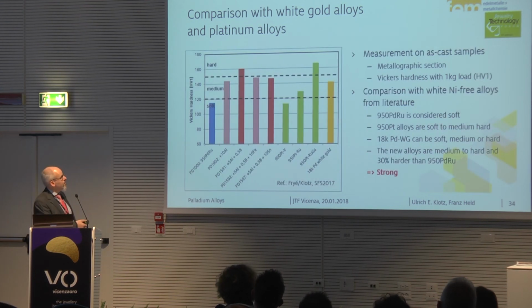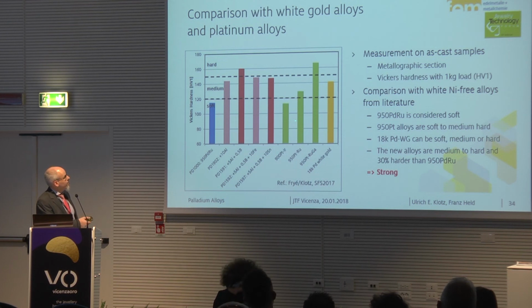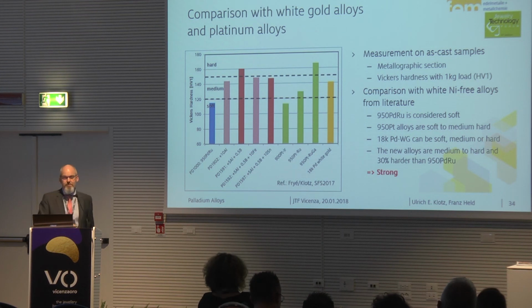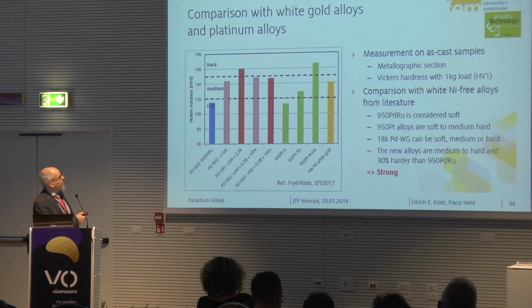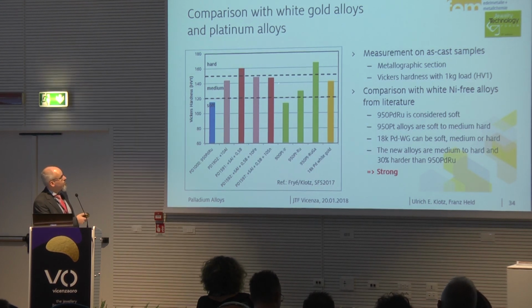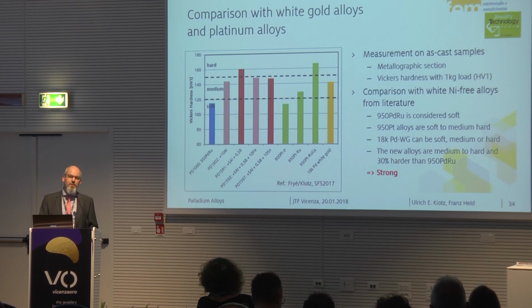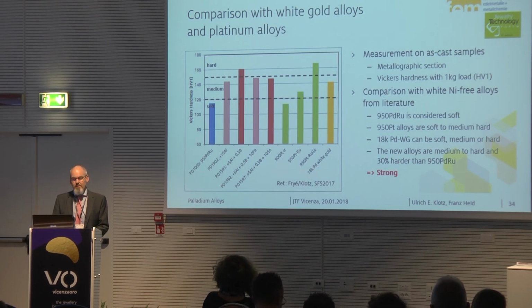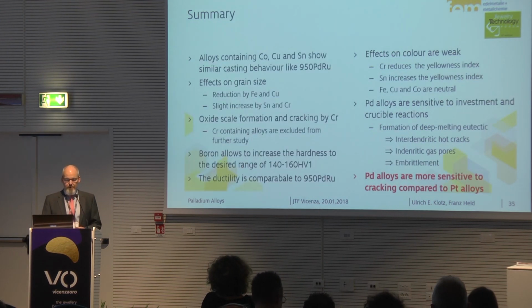And now this is the hardness diagram. So this was the standard palladium alloy, quite soft, below 120 Vickers. These are some platinum alloys where we have a great variety. Also for white gold, of course, you can have from 120 to over 200 Vickers. And the new palladium alloys are here in the range from medium to hard, so the alloys are strong enough for stone setting.